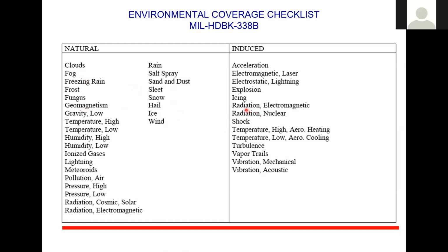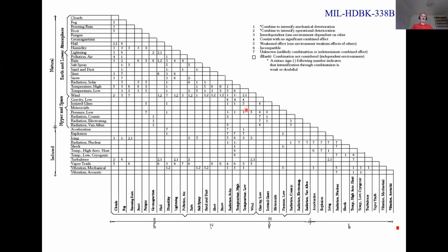And then when you have identified the relevant stresses, both natural and induced, then you can start considering their combined effects. And the MIL handbook has this kind of a table which directs you in understanding the combined effect of 2 stresses. Of course, in our practical use environments, we could have 3 or 4 or even 5 stresses simultaneously. But this is a little bit maybe not that high quality. I'm not sure if you can see all those details there. That's not the point. The point is just that we have these induced and natural stresses both in the y and x-axis. And then if we combine something, we see the cumulative effect here with numbers, and these numbers are explained here.